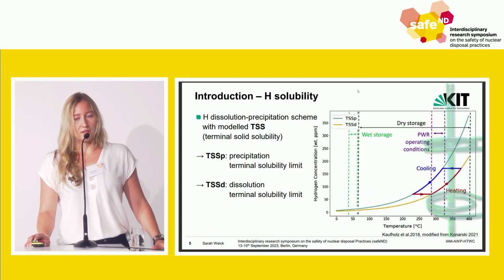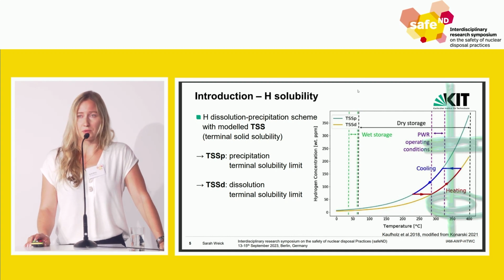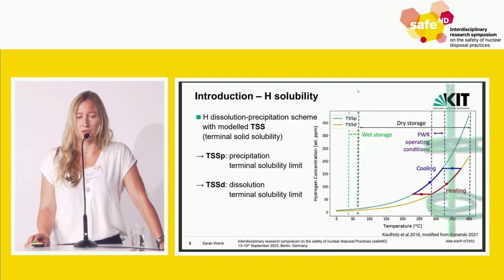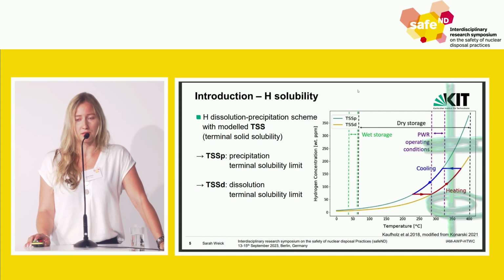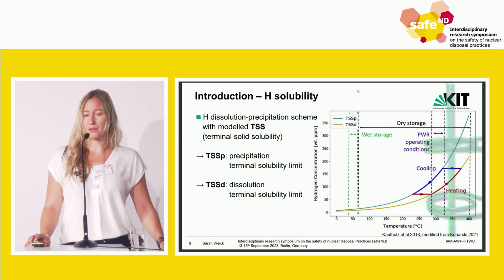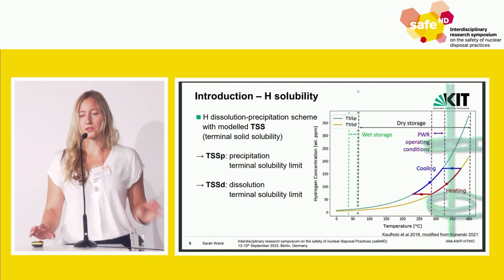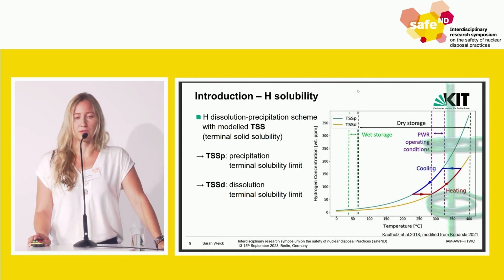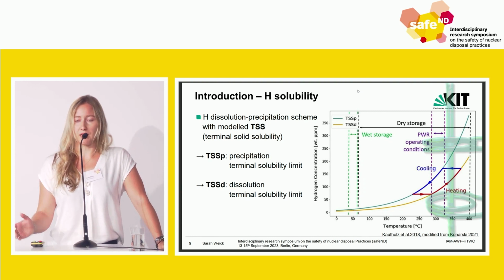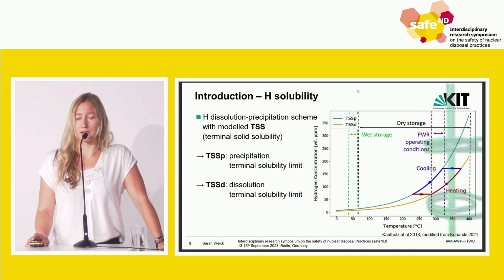The hydrogen, when in a solid state, starts to precipitate when it reaches a certain limit - the terminal solid solubility for precipitation. When this curve or slope is reached, as shown in the diagram on the right, you might start to precipitate hydrides. On the other hand, you can also dissolve the hydrides again if you reach the terminal solubility limit for dissolution. These two curves are not quite similar because of the hysteresis effect, due to different energies needed for the precipitation and dissolution processes.